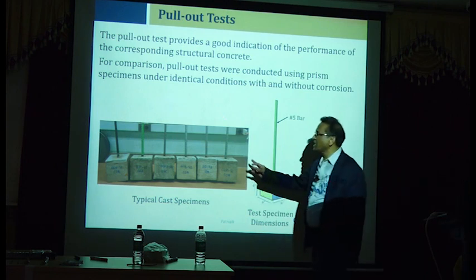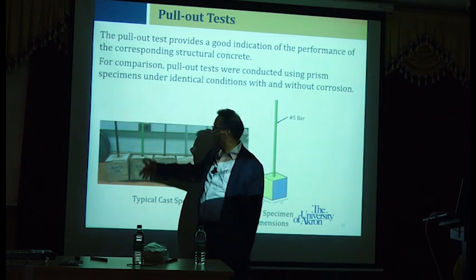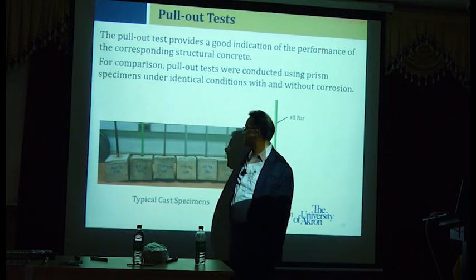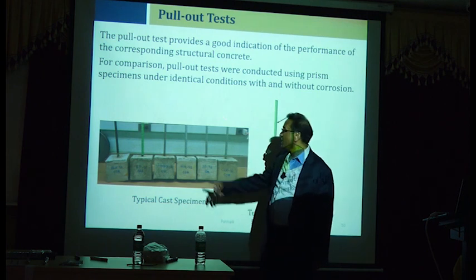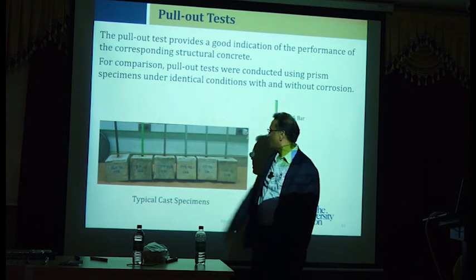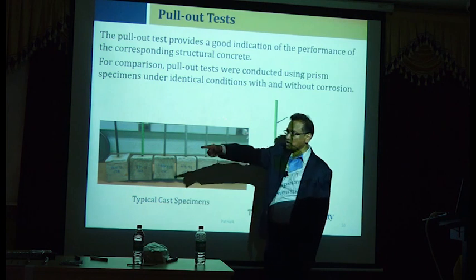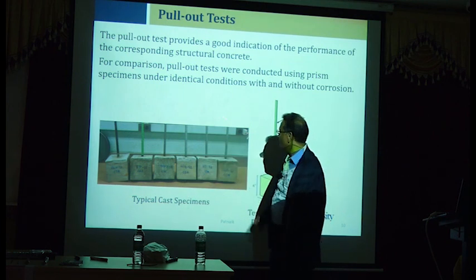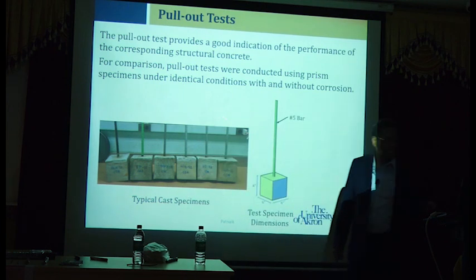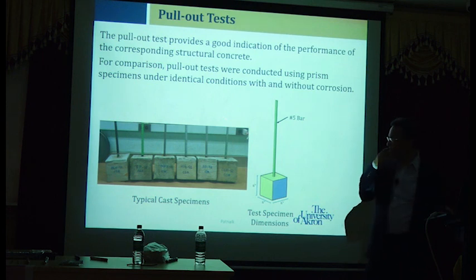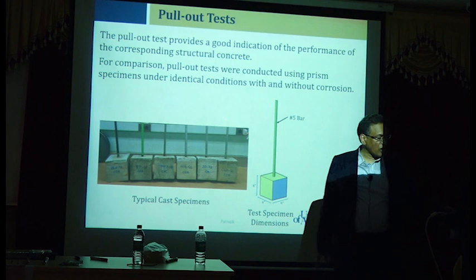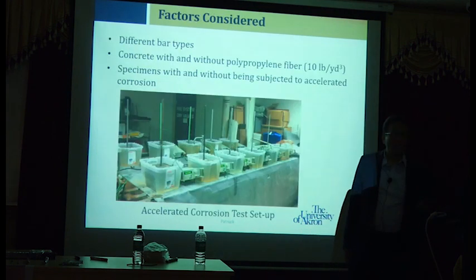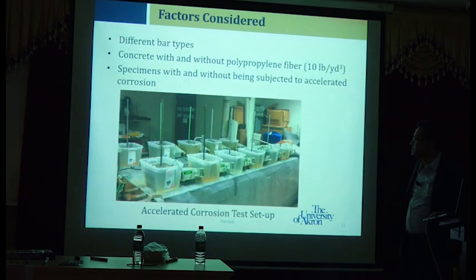In these tests, you will see there is black bar, epoxy-coated bars, MMFX, hot-dipped galvanized bars, then stainless steel bars. Some of them are sitting here, and then CGR, which is a continuous galvanized reinforcing bar. So all these are different corrosion-resistant bars, and we looked at the difference between the performance of all these corrosion-resistant bars. And we did accelerated corrosion tests.